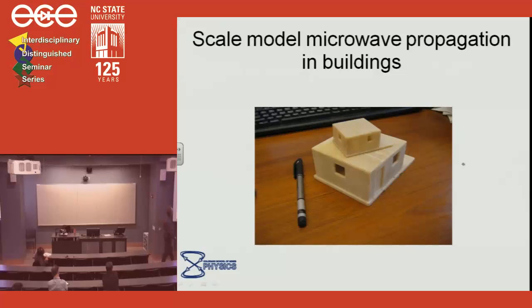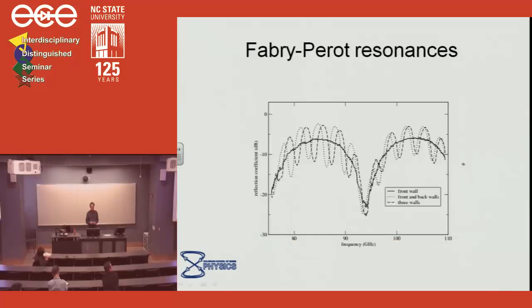There's a small room over here, and when we point the beam in this direction and sweep, basically what we see is the effect of the first wall, the effect of the room, and the effect of the back wall. Now, the way to think about this is that if you set up standing waves in the wall, the period is very small, so the Fabry-Perot fringes are going to be very far apart. Whereas if you set up standing waves in the room itself, the period is going to be large, and so the Fabry-Perot fringes are going to be very close together. And so this is actually what you get.